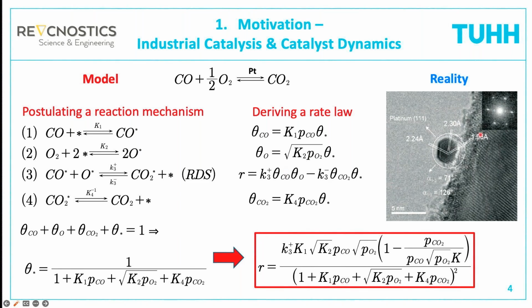And now let's take a look at reality. Here you see a platinum nanoparticle on a gamma alumina substrate. And you see that such a particle has more than one active site. There are different kinds of platinum atoms at the surface, at different facets. There are sites that are not accessible because they are at the interface to the support. There might be some sites which are in close vicinity to the support. They might be particularly active. And then we have a lot of atoms that sit on the support material. So the catalyst is in reality much more complicated than what we can put in such a simplified mathematical model.